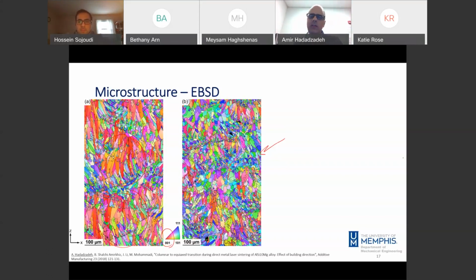So to address the first question, there are some post-processing techniques to eliminate the defects, specifically porosities and voids, by doing hot isostatic pressing, or HIP. We can close the pores by that process, which is very common in the field of powder metallurgy. However, I didn't use that. I didn't use any post-processing to eliminate the pores. To address the second question,